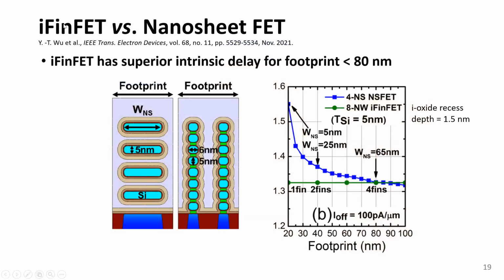So if we look at the iFinFET versus the nanosheet FET, today the industry is going to move to, they know how to manufacture nanosheet or gate all around. But even then, if we avoid forming the entire gate stack between the channel layers, we can fit more channel regions in the same height of total silicon and silicon germanium that's etched. So I think that the iFinFET provides some improved layout area efficiency. And indeed, if you look at the current per footprint, comparing the nanosheet, nanosheet is just here.